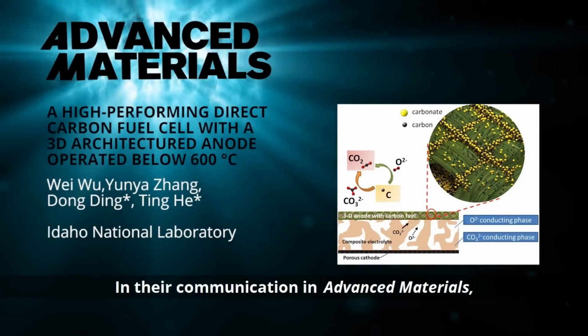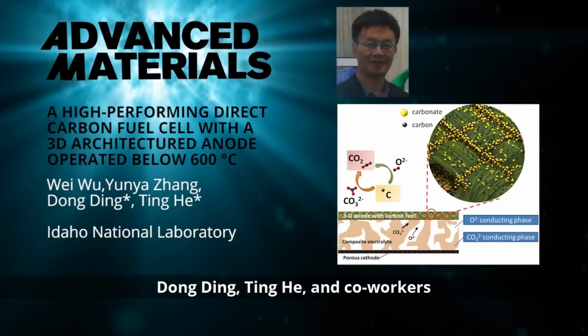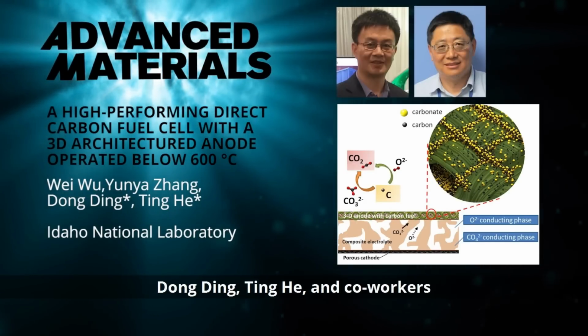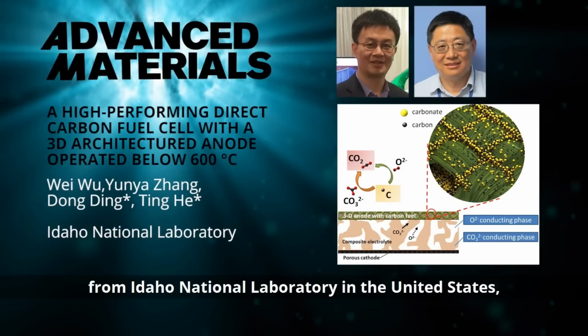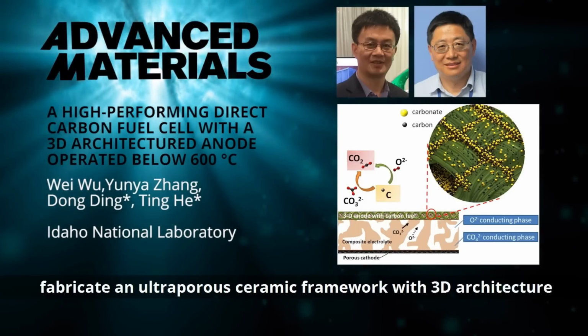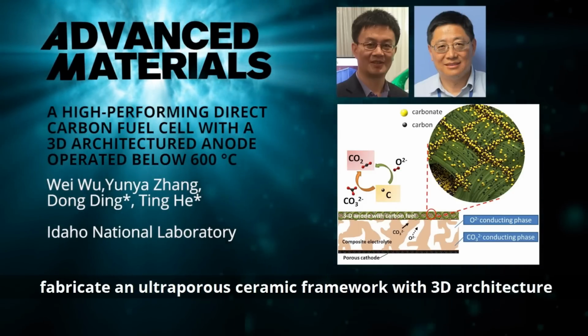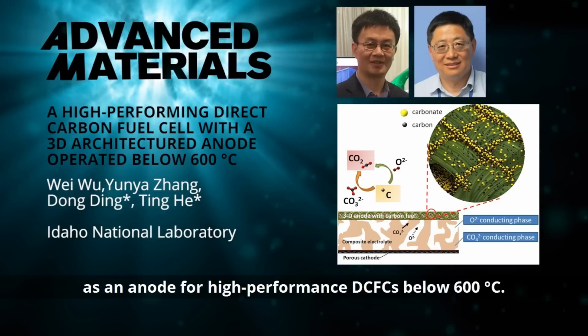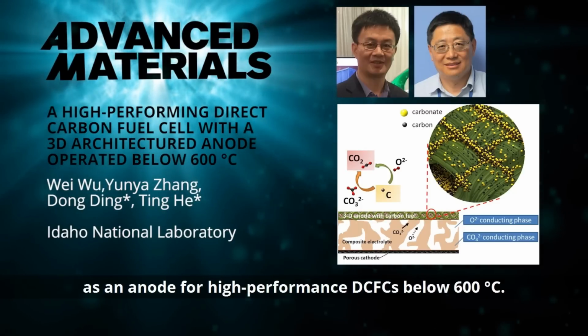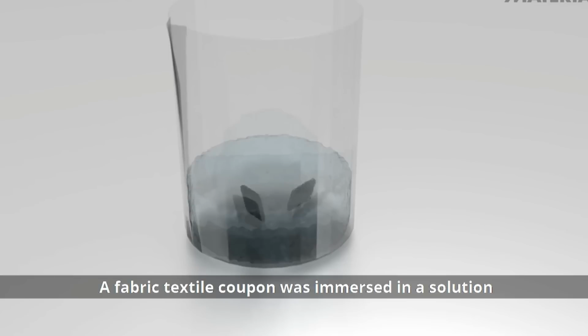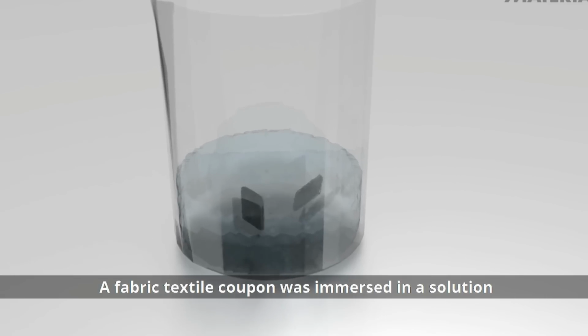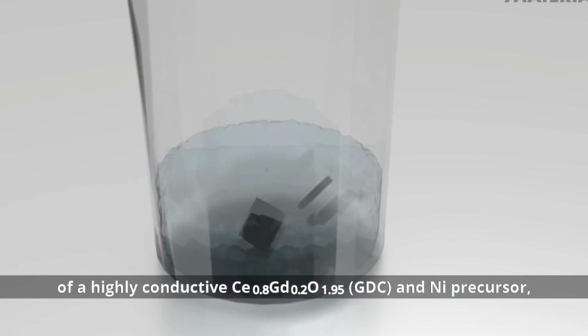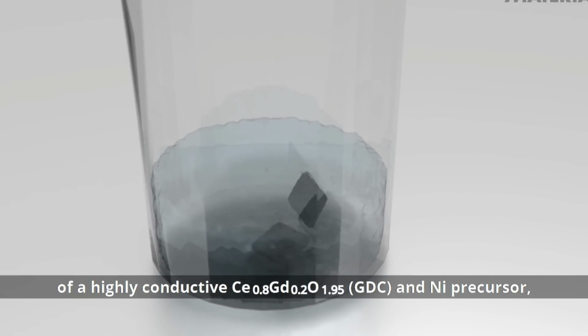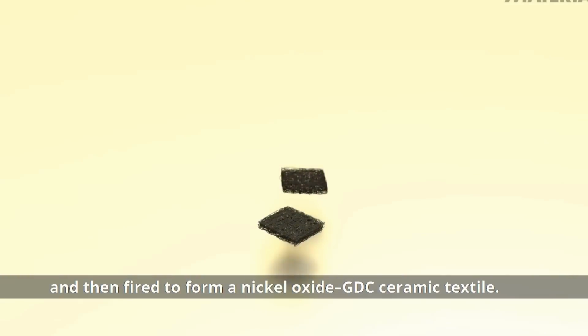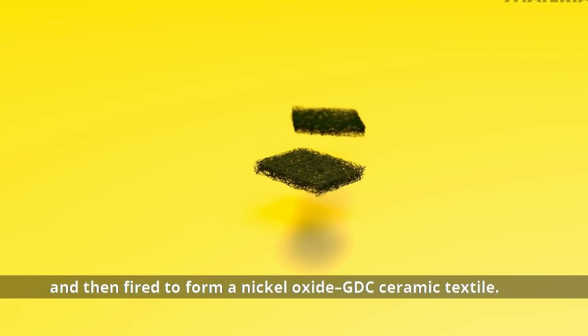In their communication in Advanced Materials, Dong Ding, Ting He, and co-workers from Idaho National Laboratory in the United States fabricate an ultra-porous ceramic framework with 3D architecture as an anode for high-performance DCFCs below 600 degrees Celsius. A fabric textile coupon was immersed in a solution of a highly conductive cerium gadolinium oxide compound, or GDC, and nickel precursor, and then fired to form a nickel oxide GDC ceramic textile.